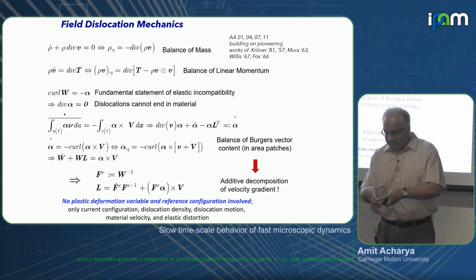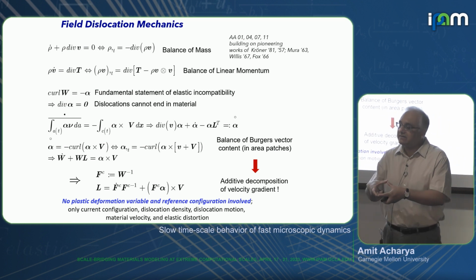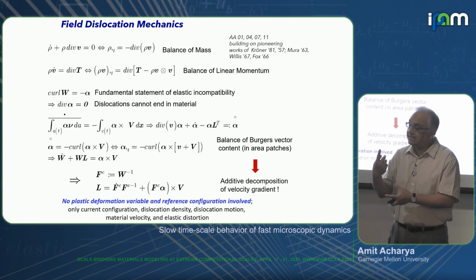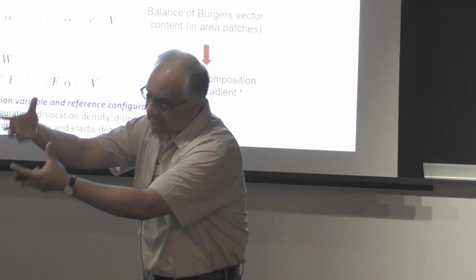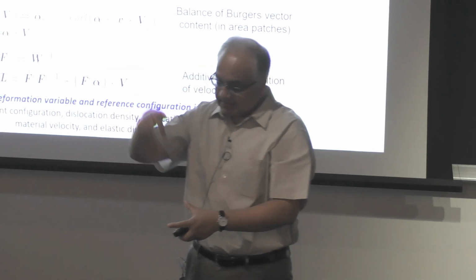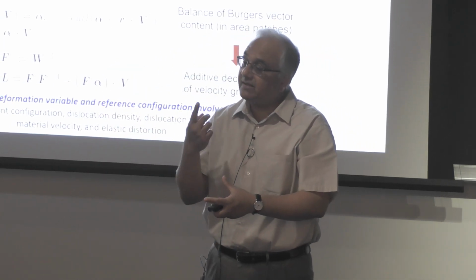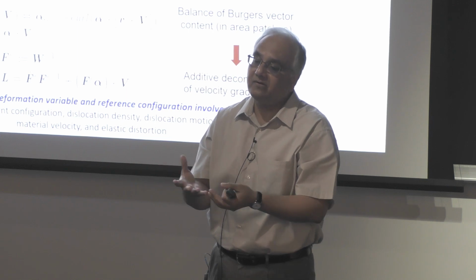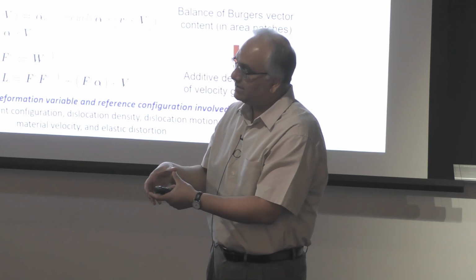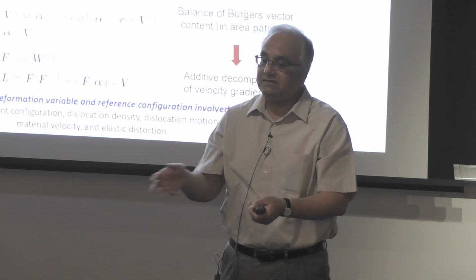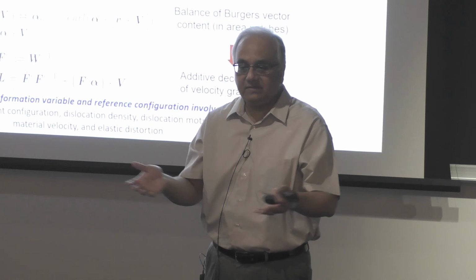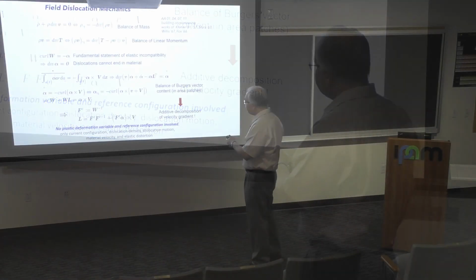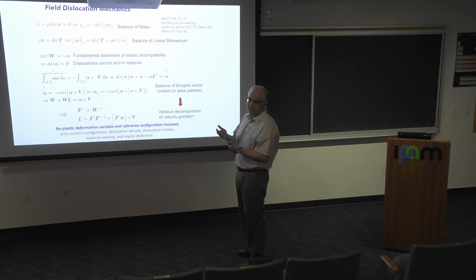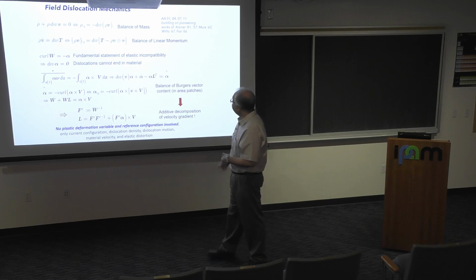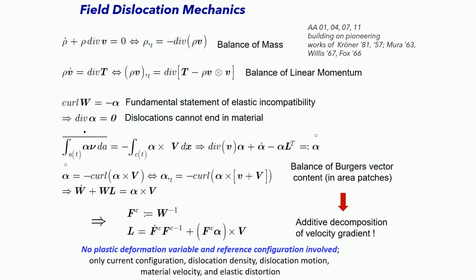And then the evolution equation is simply that you do Reynolds transport on an area patch. So these are line-like objects, not point-like objects. You basically take any area patch that's going to deform, just like we take a volume that deforms in continuum mechanics, threaded by lines, and each of them carries a Burgers vector charge, so you do the bookkeeping for how much Burgers vector is contained in an area patch. Rate of change of that is whatever's coming in minus whatever's going out because of the motion of dislocation lines, and that's essentially this statement. It becomes fancy, you've got to do the kinematics, right? But that's that, okay? And because alpha is divergence free, in the Eulerian form, it looks just like this, right?